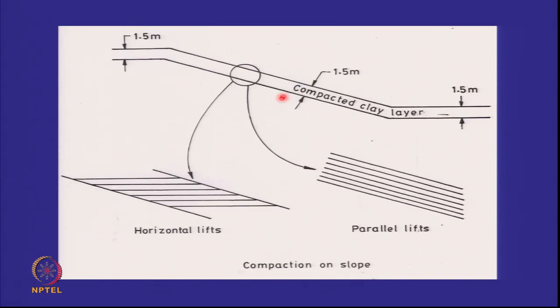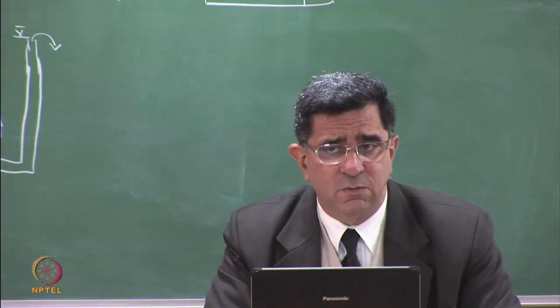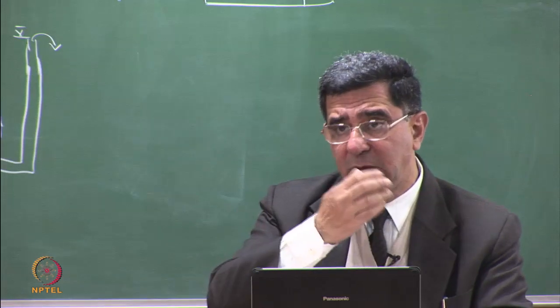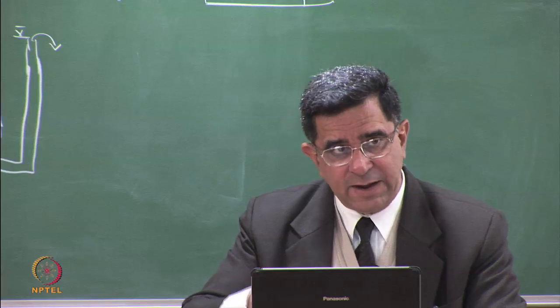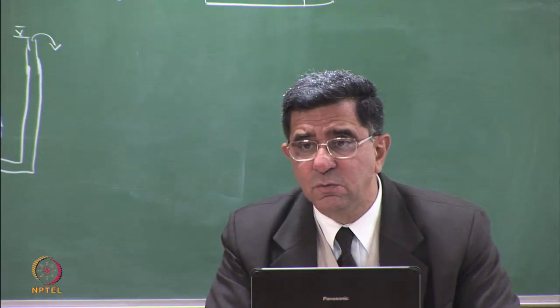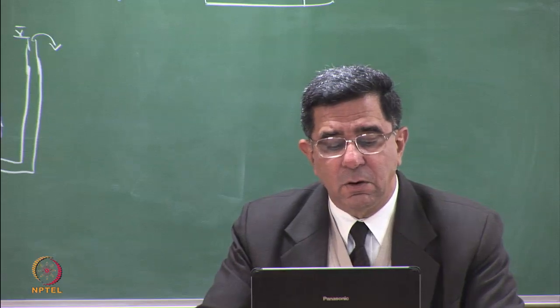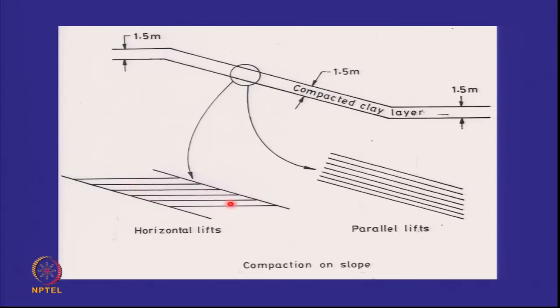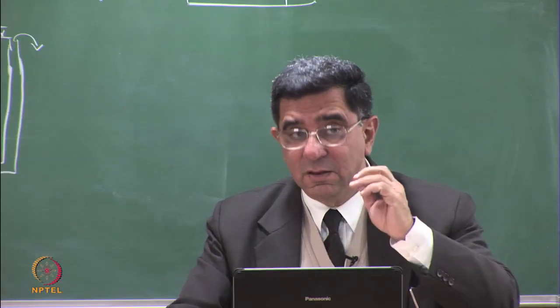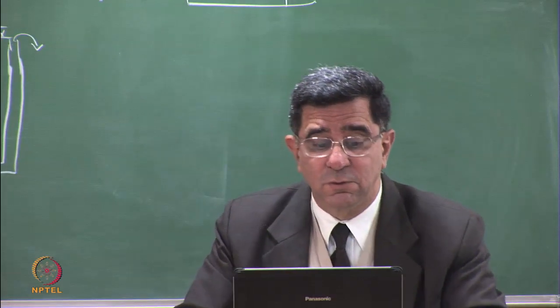The critical thing is, how do you compact the clay along the slope? Both options are available, but mostly this is a better way to do it. Because it's very difficult to move the rollers. Typically, your side slope will be 3:1 or 4:1. To be able to move a roller along that, a dozer can move with a good drive. But a roller is difficult to move along a slope. So you will be compacting in horizontal layers. And remember, if your bonding is not proper, then you are creating zones of high permeability in the horizontal direction. So it's critical that your fusion is good, and that's what a sheep's foot roller does.